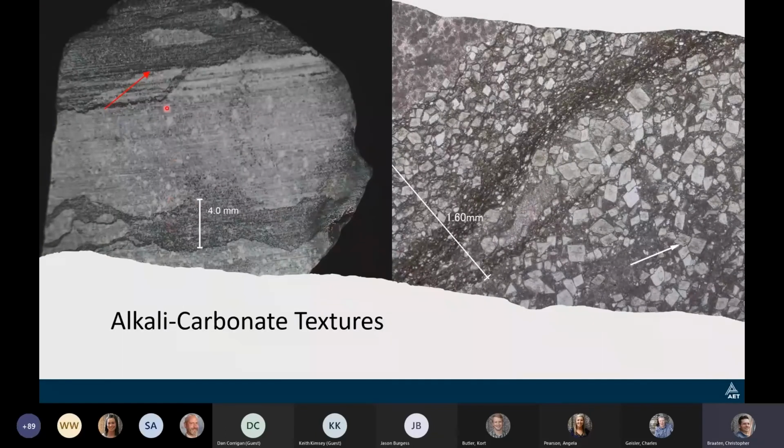So this all in the middle here, the light gray is limestone. And then these darker seams are filled. If you look over to the right, this is a thin section image of one of those seams. And you can start to see that it's got that micritic calcite. It's got the euhedral dolomite rhombs. It's got some other insoluble residue up here. Some of these minerals are probably quartz. Kind of interesting though, I've only seen this dolomitic texture personally in my career in these seams, and I've seen these seams here